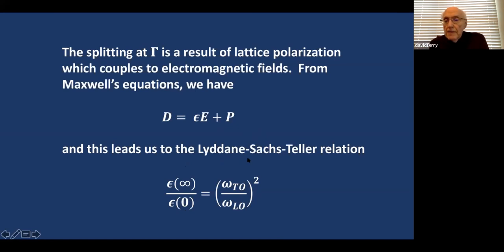Now, if you take a material, for example, like moly disulfide, a monolayer material, you'd say, well, it's a metal, moly, and a couple of chalcogenide atoms, sulfur, and they should have different charges and they should have something like this, but they don't have any polarization because at 0, at the gamma point, which is the small k where you're going to get photons into the system, these 2 dielectric constants are exactly the same. And these 2 frequencies are degenerate. And so there's no polarization in moly disulfide. And that means that the scattering process from that polarization, which is called the Froelich interaction, doesn't exist in moly disulfide. So that's an important thing. If you look at this spectrum, that's a strange material because you would expect things that aren't there. So it's a kind of a sanity check.